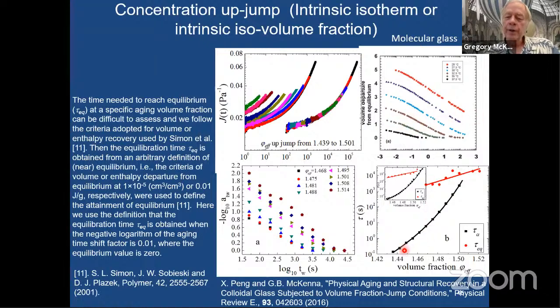It's similar. We have a strong decoupling between the alpha time, this is the alpha time, versus the time it takes to actually get into equilibrium, which is this time. And you do see some differences in molecular glasses, but they're not as big as what we're seeing in these colloidal glasses.